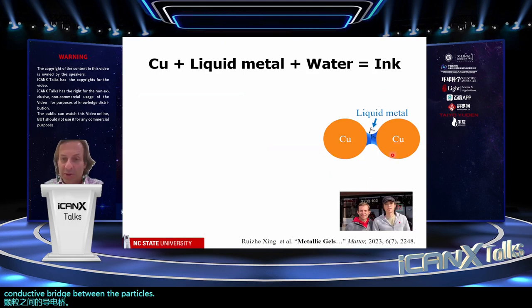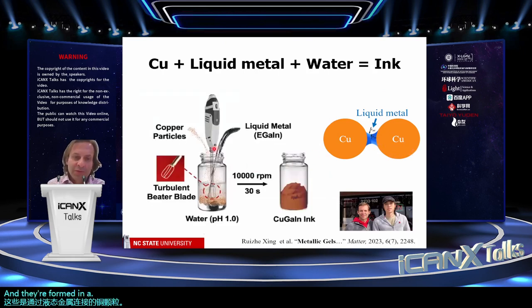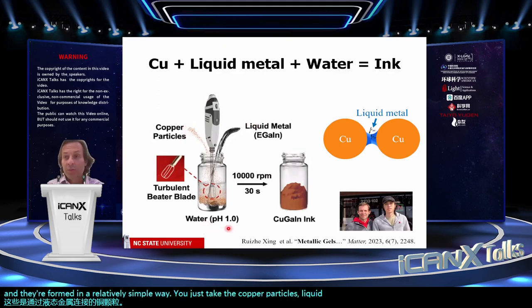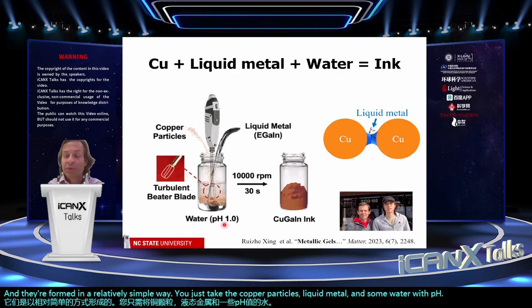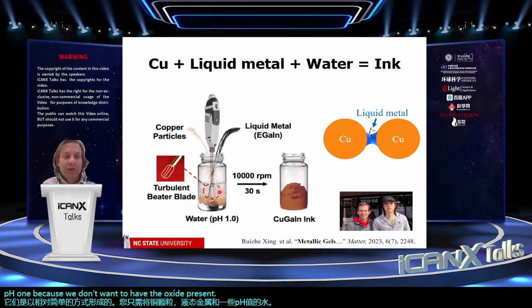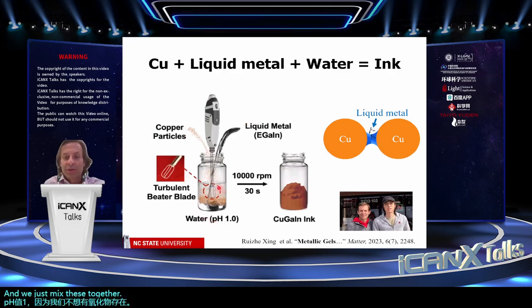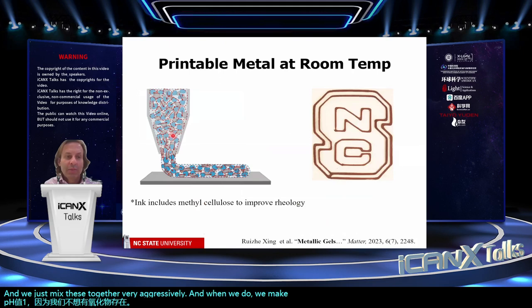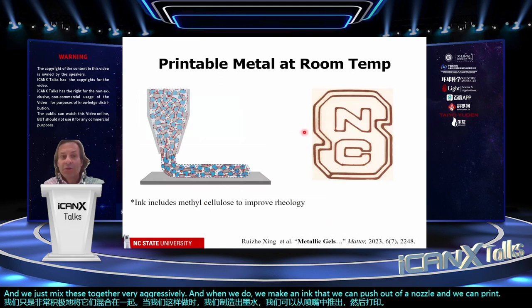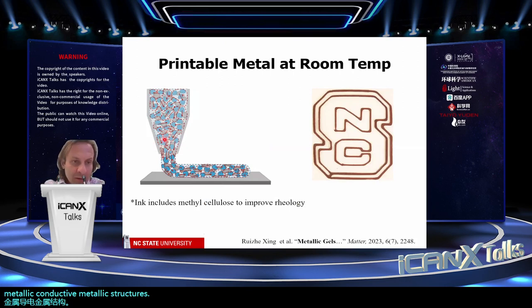So here is what we did. These are the copper particles connected by the liquid metal, and they're formed in a relatively simple way. You just take the copper particles, liquid metal, and some water with pH 1. pH 1 because we don't want to have the oxide present, and we just mix these together very aggressively. And when we do, we make an ink that we can push out of a nozzle, and we can print conductive metallic structures.